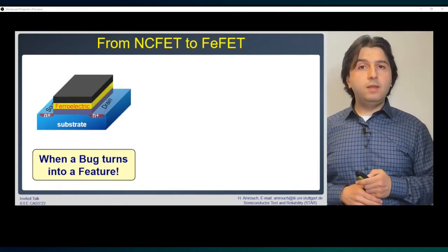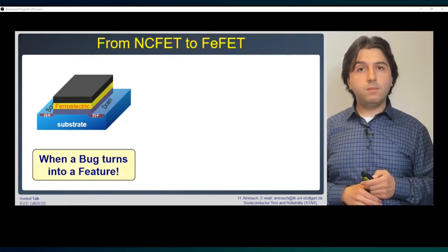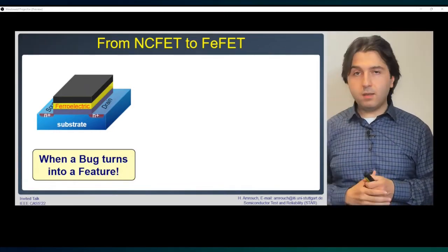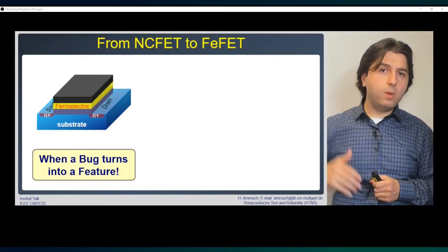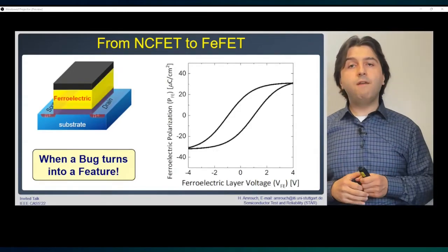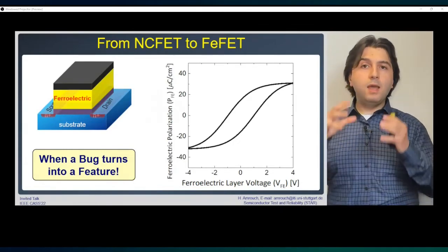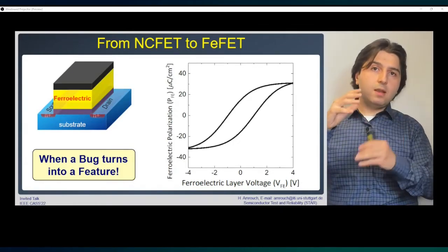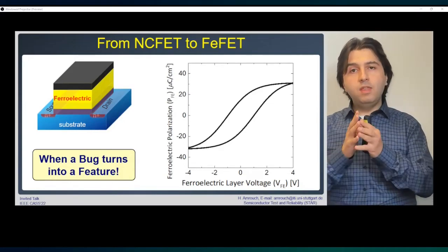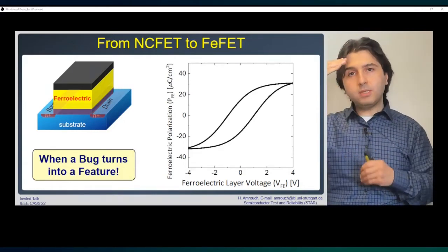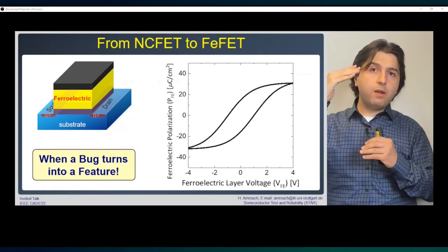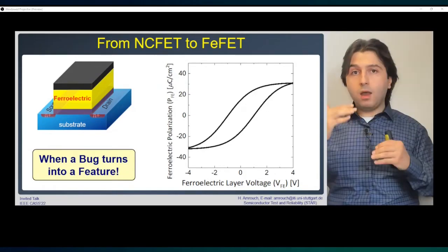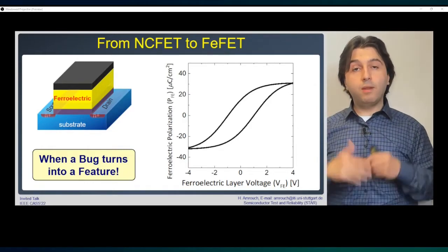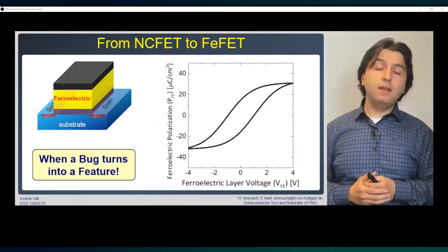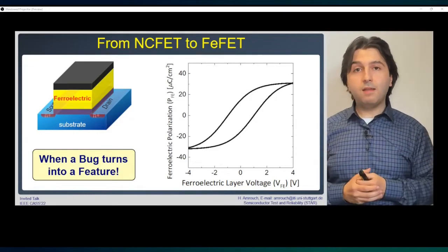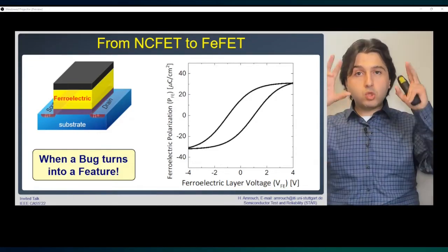if we increase the thickness of the ferroelectric layer above a certain limit, let's say 5 nanometers, 6, all the way up to 10, the so-called hysteresis effect starts to appear because the dipoles within the ferroelectric layer start to be polarized. If you apply a negative or positive voltage or electric field, this will polarize the dipoles either up or down. And this polarization remains even after removing the electric field, and therefore we are able to store this.